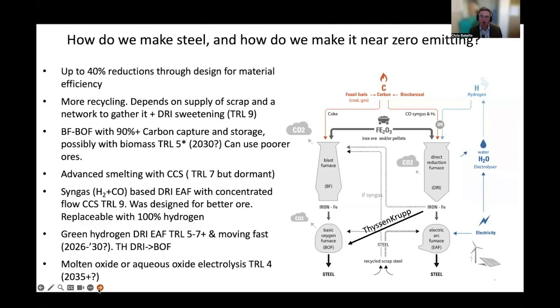There is another process that was pioneered in the 1970s called direct reduced iron furnaces, where we pelletize the iron ore. We typically use gas as the reductant. So we break the methane or the gas into hydrogen and carbon monoxide. We pass that reduction gas over the iron ore pellets. And the carbon monoxide, when it oxidizes to CO2, provides the heat. And then most of the oxygen is carried away by hydrogen. We can potentially tweak that process and make it 100% hydrogen if there's an external heating source.